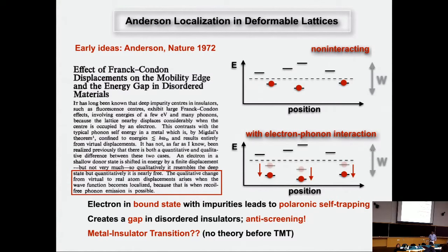The first hint of what could be important was put forward by none other than our favorite hero, Mr. Anderson, in 1972, who pointed out that if you form bound states, then something has to happen which is not happening in metals. In metals, the electron is zooming around, and the lattice deformations don't do much because the electron is fast and the phonons are slow. But once you form a bound state, then the lattice will accommodate this to lower its energy, to dig a potential well.